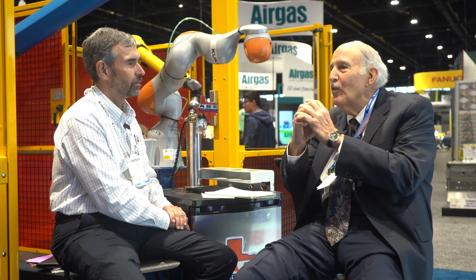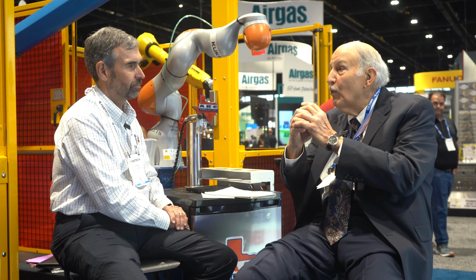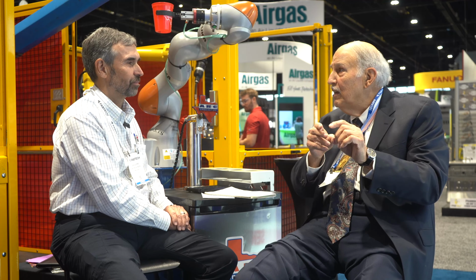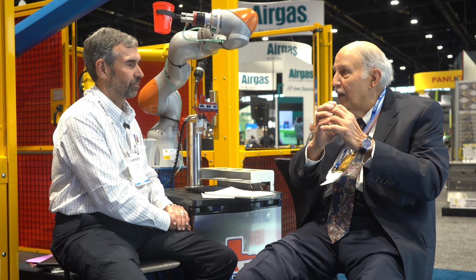And all that time, they didn't know that they were looking at ductility dip cracking or solidification cracking. Solidification cracking happens when you have a liquid phase present and stress, because the tensile strength of a liquid is zero. But in ductility dip cracking, it's solid state. So everything solidifies without any cracks, but then by the shrinkage stresses, you can actually have cracking in the thing as you go. And some people have cracking with 625. And we're working on a project right now to make 625 more resistant to cracking.